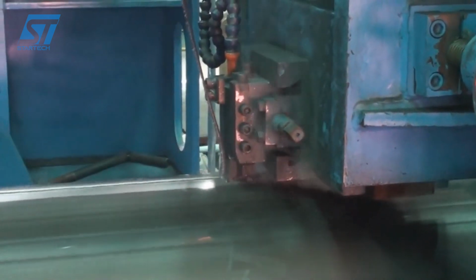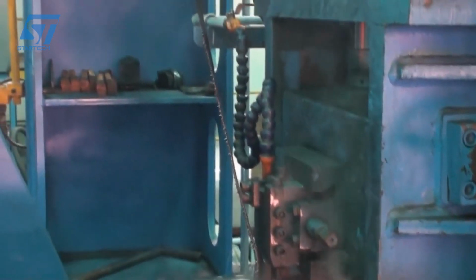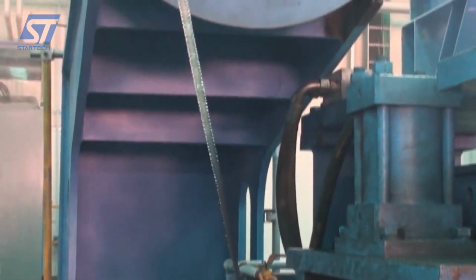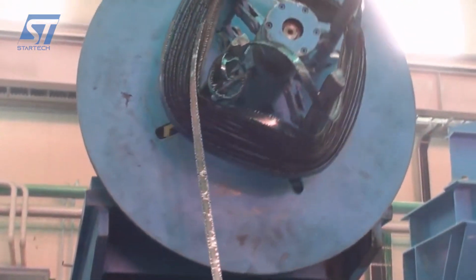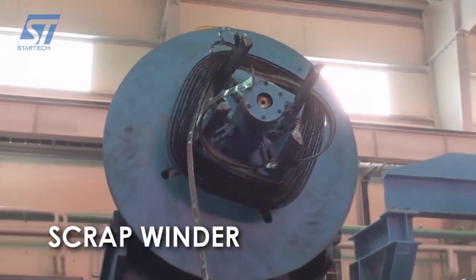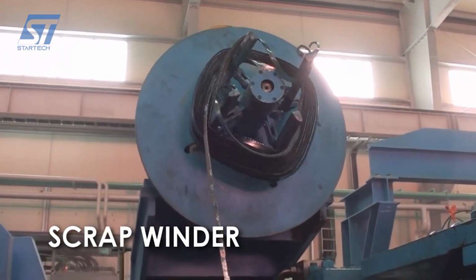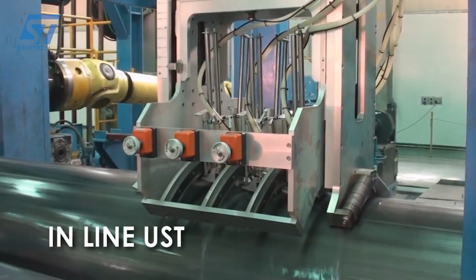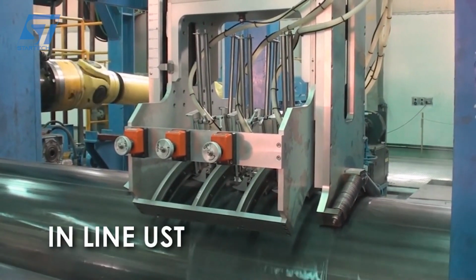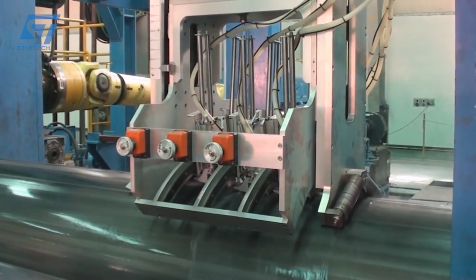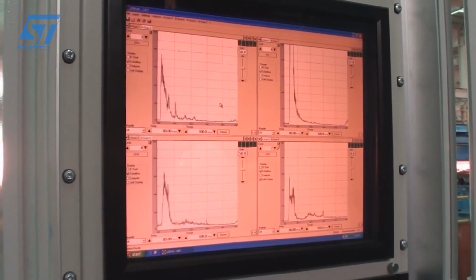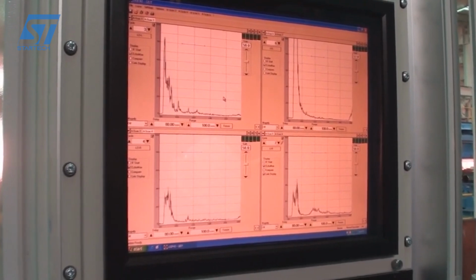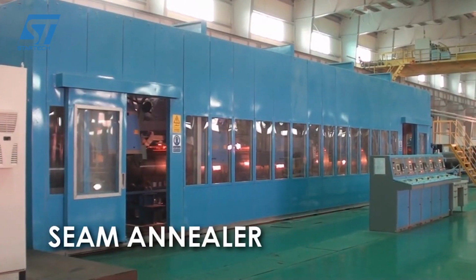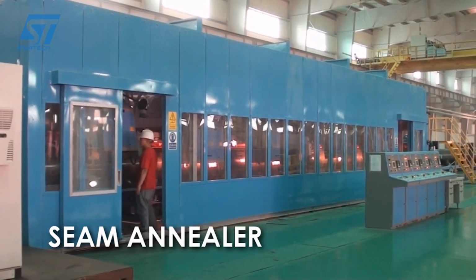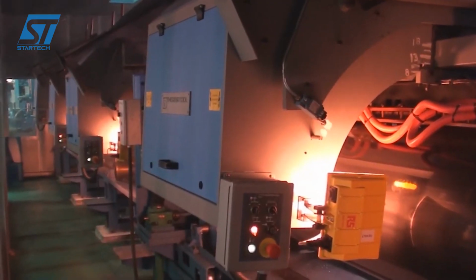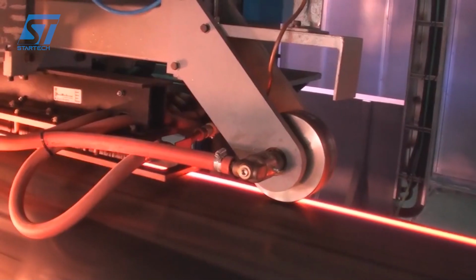Traditional tube forming methods often use discrete rolling steps, in which the steel strip is bent step by step by pairs of rollers. This method can cause local stress and deformation in the material, especially when producing thin-walled tubes. The Yoder cage forming system overcomes this disadvantage by forming continuously and smoothly, minimizing stress and deformation. It uses a series of rollers arranged in a special structure, forming a cage around the steel strip. The steel strip is guided through this cage, and as it moves, it is gradually bent and shaped into a tube. This process is continuous and smooth, with very small shape changes at each stage.